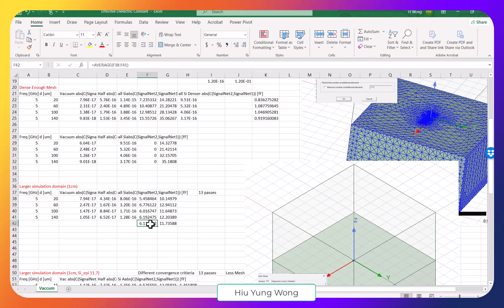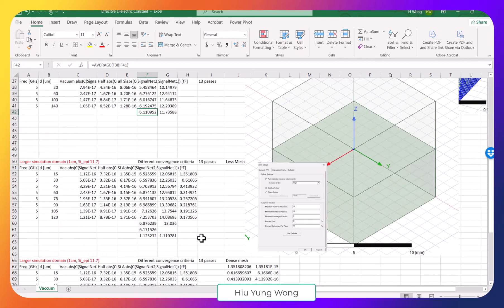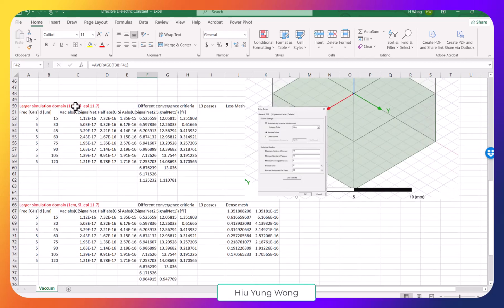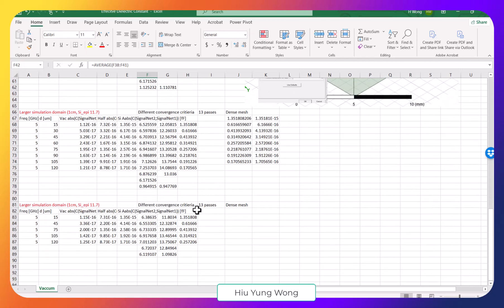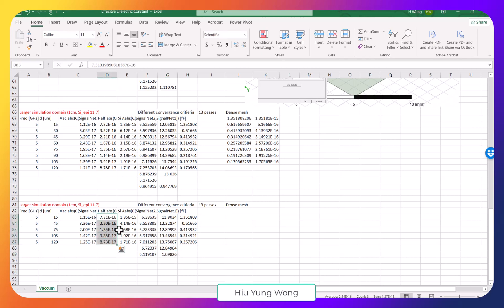With a denser mesh and different passes, the silicon ratio came out as 12.8 instead of 11.7 — about 9.8% more than expected. For the real half structure (top vacuum, bottom silicon), the value was 6.7. Dividing 6.7 by 1.098 to correct for the same proportional error still gives about 6.1, confirming that the effective dielectric constant for a superconducting chip with silicon substrate and vacuum on top is approximately 6.1.